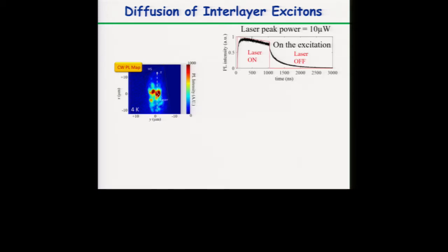All right, so now let's do the same. This is the same sample, right? At the high power, this is all low temperature. Now we can collect in a line cut, so we can collect in different positions of this line cut while still exciting in the same position. What we can do now is also look at the time dependence. We can find out how long it takes for an interlayer exciton to arrive at a certain distance away from the excitation spot, and that's what we did here.